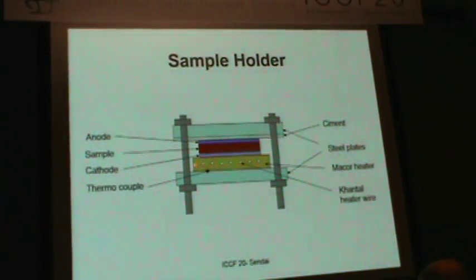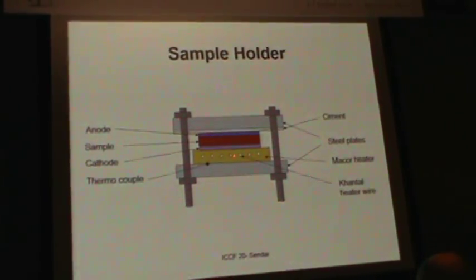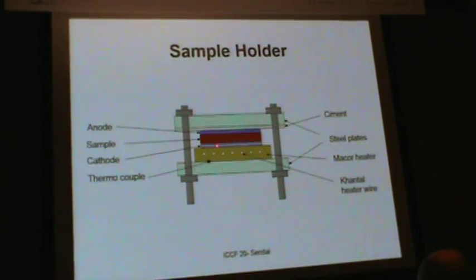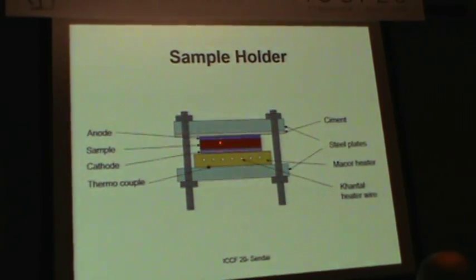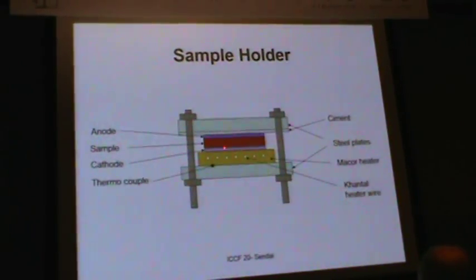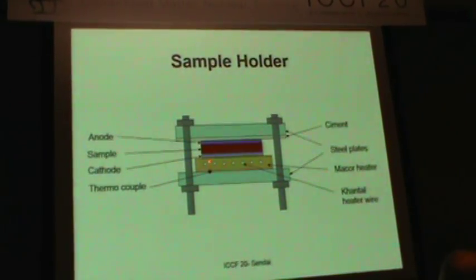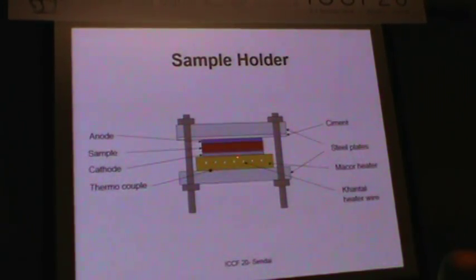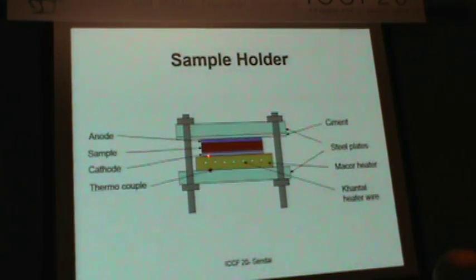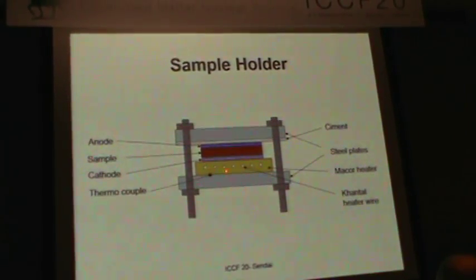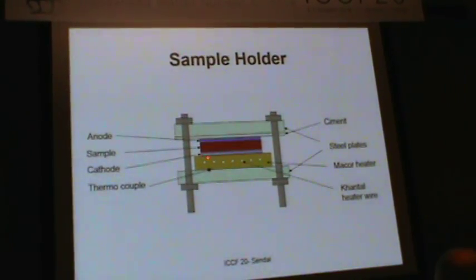and I can pass the current between those two plates. So first I have to heat up the sample to a pretty high temperature so that conductivity happens, and then I can put a current through the two plates, and the proton conductor will be active. I put a thermocouple here, in between the cathode and the heater, to measure temperature also.